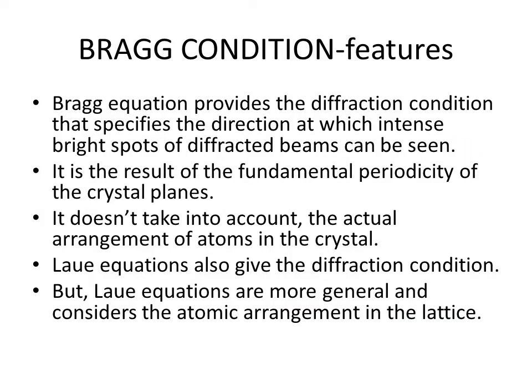Now when you look at the Bragg condition, you will see that it is actually the consequence of the periodicity of the crystal planes. In each of these crystal planes there are atoms which are arranged in a specific manner, but in the Bragg derivation, the way in which these atoms are arranged in each of these planes is not taken into account. So in that context we will see Laue equations. Laue equations are more general compared to the Bragg condition.